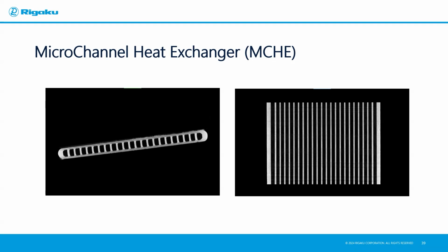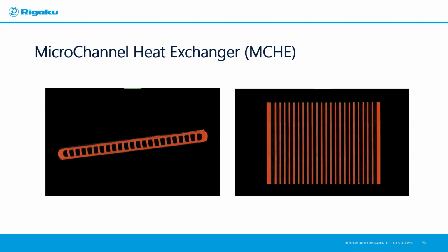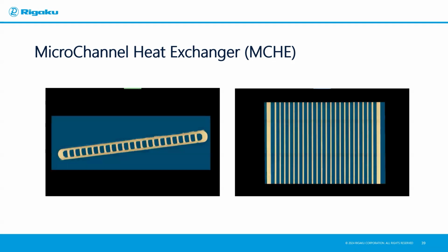So this is like our LED example where we could simply use histogram thresholding to segment. In that case, we can pick the brightest peak to label the metal portion and say, okay, everything outside is also air, and it's easily segmented. At this point, you could look at the microchannel characteristics, the thickness of the metal parts.